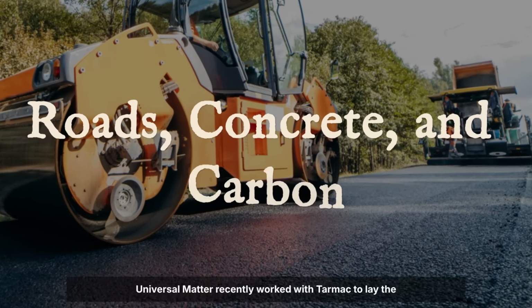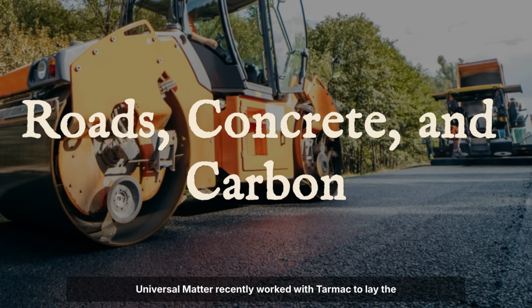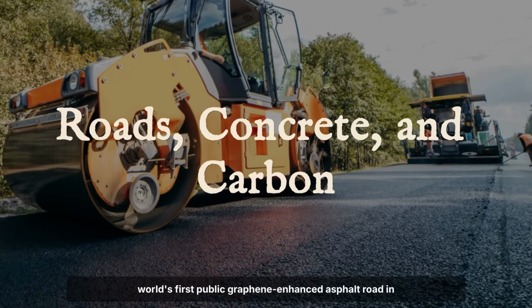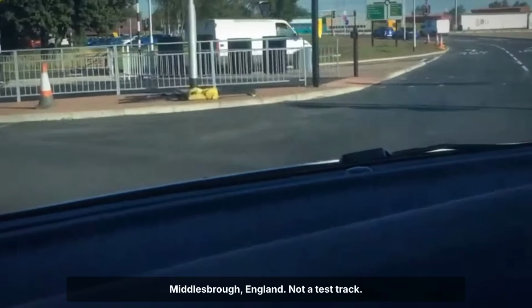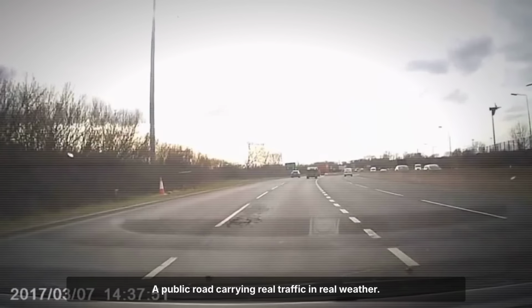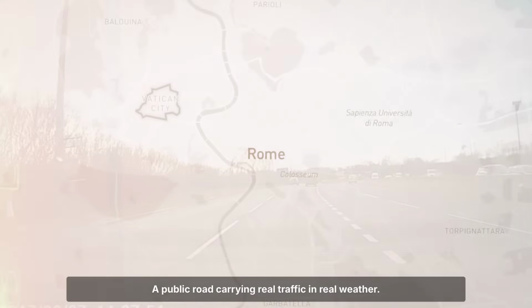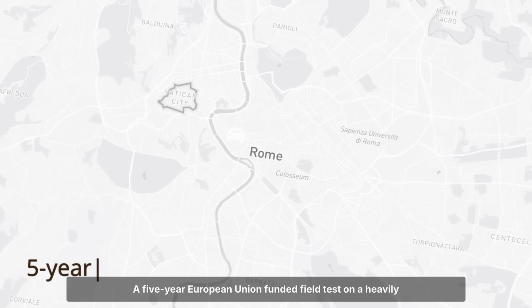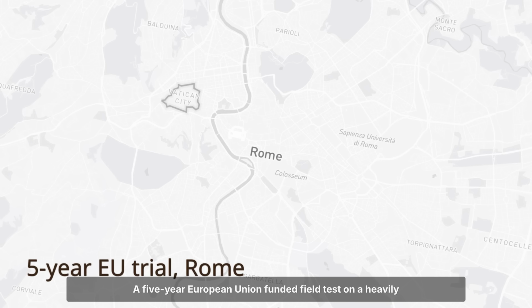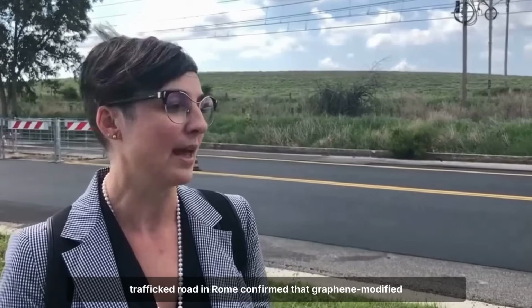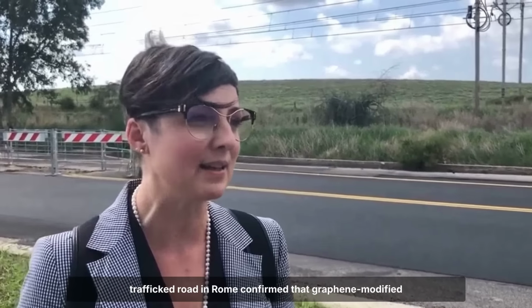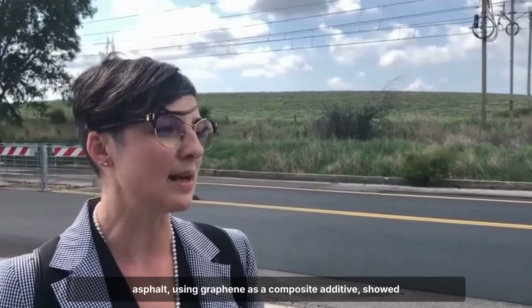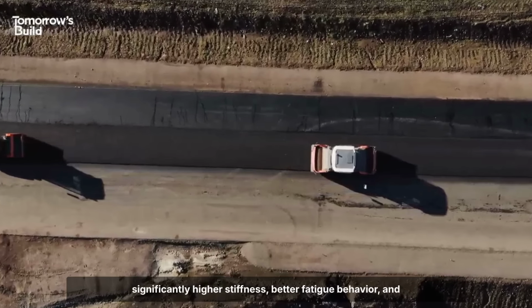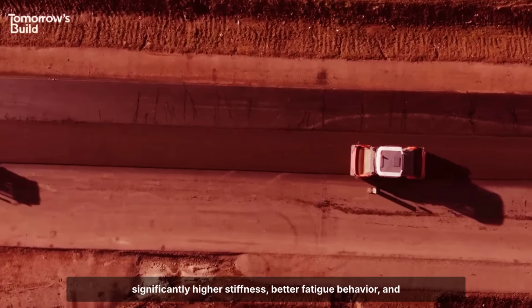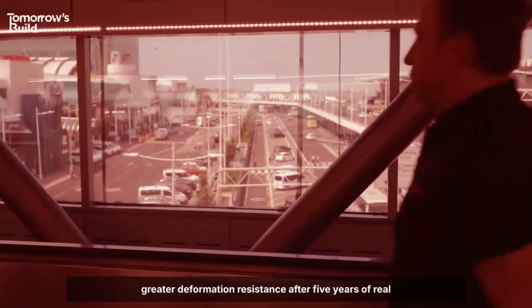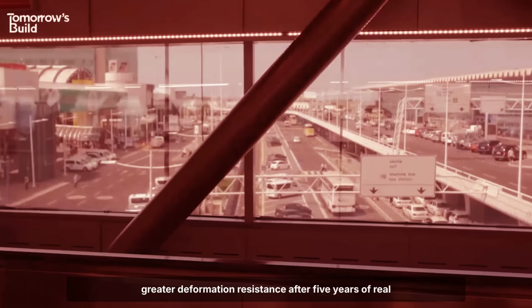Universal Matter recently worked with Tarmac to lay the world's first public graphene-enhanced asphalt road in Middlesbrough, England. Not a test track. A public road carrying real traffic in real weather. A 5-year European Union-funded field test on a heavily trafficked road in Rome confirmed that graphene-modified asphalt, using graphene as a composite additive, showed significantly higher stiffness, better fatigue behaviour, and greater deformation resistance after 5 years of real traffic.